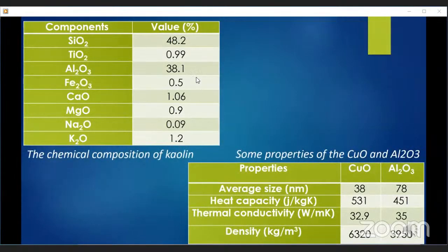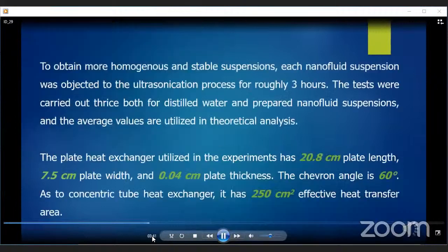It is clear in these tables, the chemical composition of kaolin and some properties of the copper oxide and alumina nanoparticles can be seen. It's clear in these tables that metal oxides have high thermal conductivity values. In order to obtain more homogeneous and stable suspensions, each nanofluid suspension was subjected to the ultrasonication process for nearly 3 hours. The tests were carried out 3 times, both for distilled water and prepared nanofluid suspensions, and the average values are utilized in theoretical analysis.